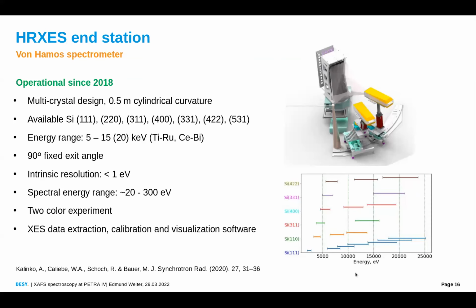The high resolution X-ray emission end station, the Von Hamos spectrometer, this is Alexander Kalinko's work. And it's operational since 2018. It was developed in several steps. Meanwhile, the setup can take up to 16 bent crystals, and is working with these 16 bent crystals. There's a large collection of crystals. I must admit, I don't know if from all of them there are 16 available, but all of those are available, so that it's covering really the whole energy range between 4,000 electron volts and up to 25,000 electron volts.